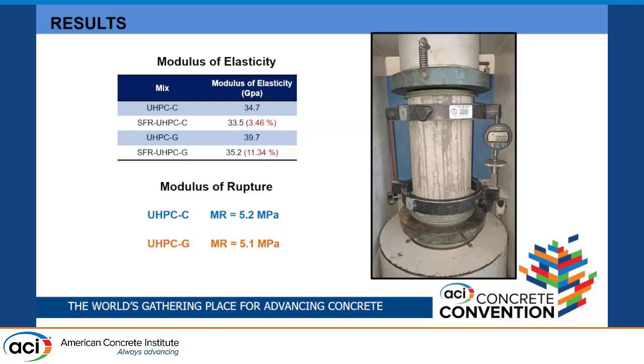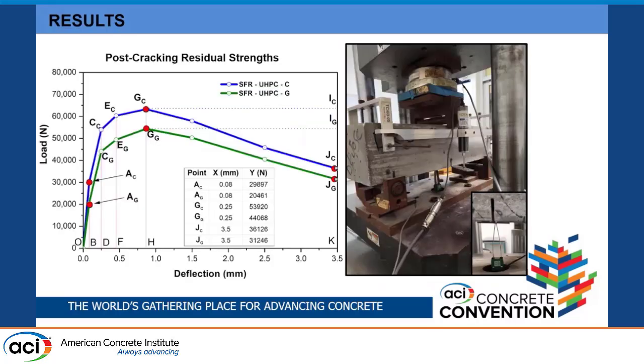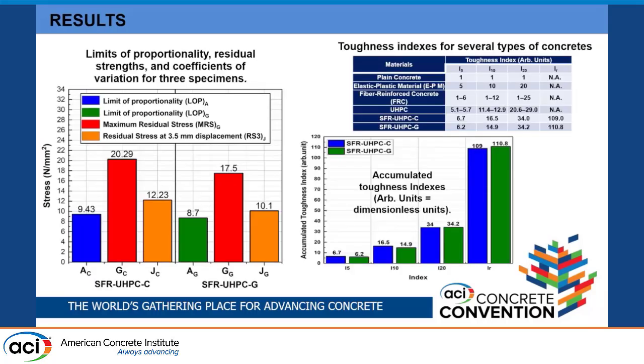In the case of modulus of rupture, okay, we make some beams. That's the strength that we obtain for the beams without fibers. And these are the graphics that we obtain for the two concretes with fibers. So as you can see, those points that appear in the graphics, the A means when the first crack appears in the test, and the others are the toughness indices that are established in the literature to determine the toughness of the material provided by the presence of fibers. Okay, so these are the limit of proportionality.